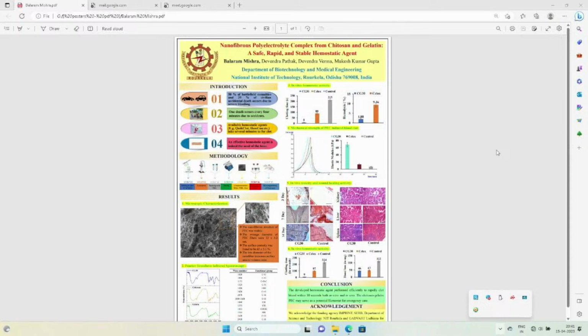Surface area, then surface area to volume ratio will be much higher. Here, I have not shown the data, but in BET analysis, we have found around... So we have done surface characterization and chemical characterization. In chemical characterization, the polyelectrolyte complex was found to be gelatin and chitosan bound with electrostatic interaction and hydrogen bonding. In the clotting test, the in vitro clotting time we found